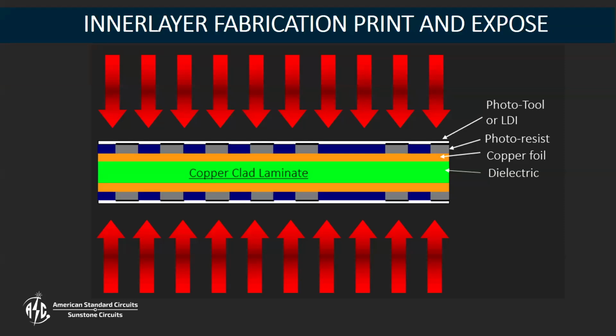and then brought back together and laminated together. So the first step to that is we take this core material, copper-clad laminate, that has copper on both sides of the right thickness, whether that's 1/2 ounce, 1 ounce, 2 ounce, 3 ounce, 10 ounce, whatever that might be. Layer 2 and layer 3 are commonly the same thickness, but can be different depending on designs. But we take these panels that are copper, laminate, copper. We apply a photoresist to both sides of it, which is a photosensitive polymer. And what we're going to do is we're going to image that with our LDI in this case.